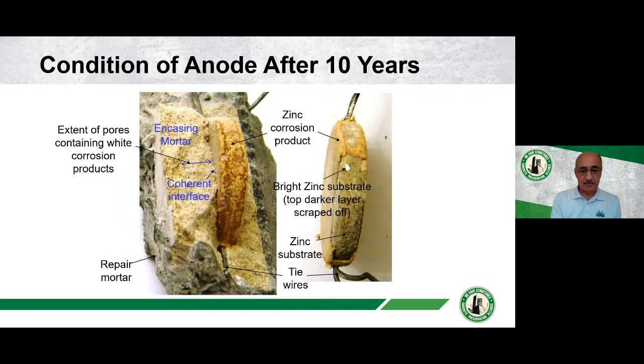And at 10 years, we were able to take out an anode from an adjacent patch repair, not the actual monitored area, but one close by, which was set at the same time. So we thought the same thing would have happened to that. We took it apart basically and had a look at it. We could see that that was the original zinc core. It's now covered in corrosion products, which if they're removed, you can see that there's still zinc underneath. By scraping it, you can see this bright zinc still underneath. There's no signs of distress at the interface.